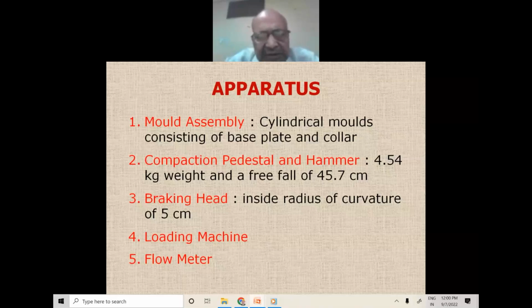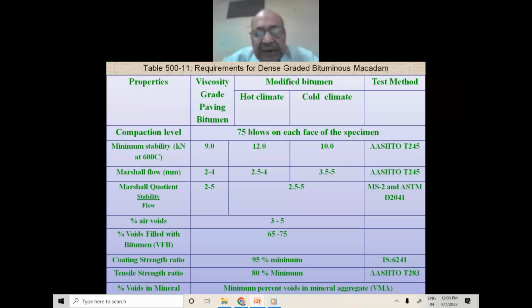Now, how to do the mix design? The procedure is the same as we do the mix design for normal bituminous mix. So briefly, I will review the mix design procedure. It involves various steps: selection of the aggregate, selection of the plastic waste, selection of the aggregate gradation, proportioning of the aggregate to meet the required gradation, and selection of the bitumen. Selection of the bitumen is also important. If we are using plastic waste, the use of VG40 should be avoided.